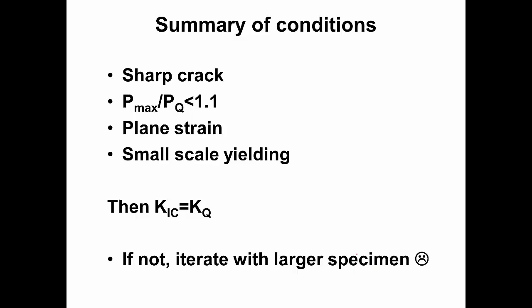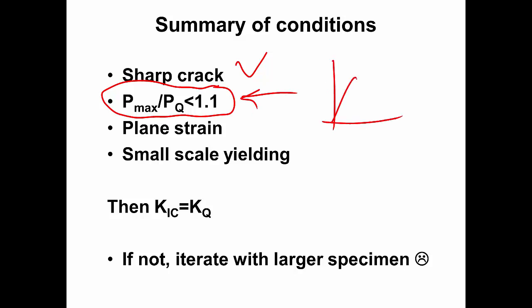So, in summary, you need a sharp crack, which we usually do by prefatiguing the specimen. You need some conditions for the load, and in particular, we are interested in the case where you may have multiple failures indicated by peaks in the load opening displacement. As long as the first peak and the main peak do not differ by more than 10%, then it's okay. If not, there is something wrong. There is an indication of some problem in the specimen.